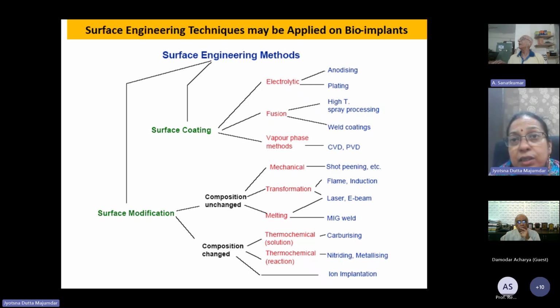So they do bioactivation of the surface in two ways. The first way is by mechanical roughening. The second way is by application of a bioactive coating. If you talk about coating, there are many different varieties of coating techniques available. And while applying a coating material, you have to choose the proper coating technique. That's very important. So in the next few slides, I would like to show the effect of plasma spray deposition of hydroxyapatite coating on the surface of the implant, and also we will try to show the effect of replacing sand blasting with laser surface texturing for improving the bioactivity of titanium based implant.